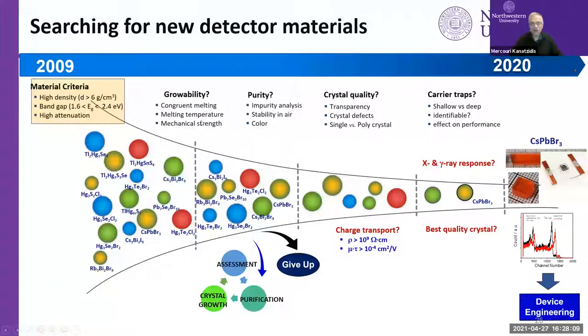So our criteria were, for example, growability. Is it easy to grow? Is it congruent melting? Does it decompose? Does it have mechanical strength? How pure is it? We did impurity analysis. Is it stable in air? What is the band gap? What are the likely crystal defects, and so on. And this was some of our criteria.